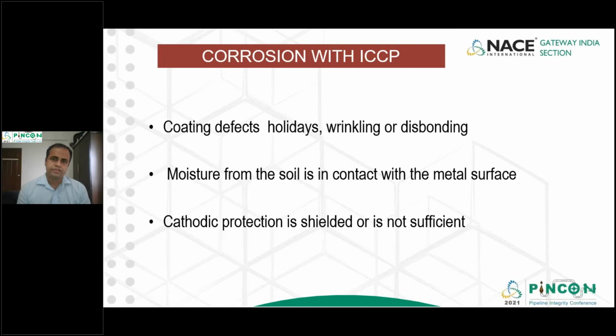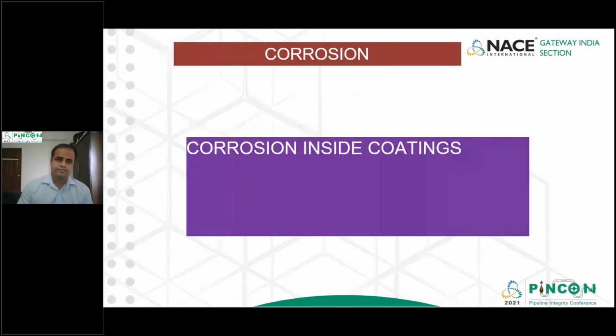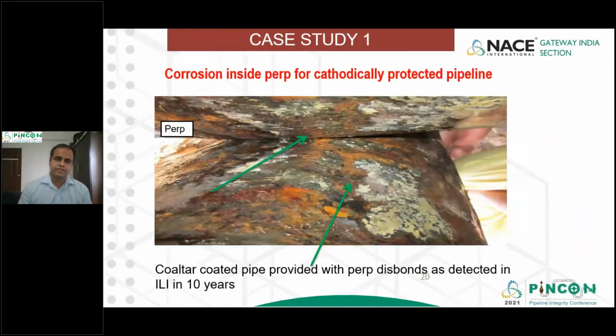The corrosion with ICCP in place. Why? Because there are coating defects, the holidays, the disbonding. There is moisture from the soil which is in contact with the metal surface always, because the pipelines are buried in the ground. And the cathodic protection current is expected to reach the holidays in the coating. Cathodic protection is shielded sometimes and is not sufficient to ensure a current density to carry out the required polarization of the metal. So what happens here?